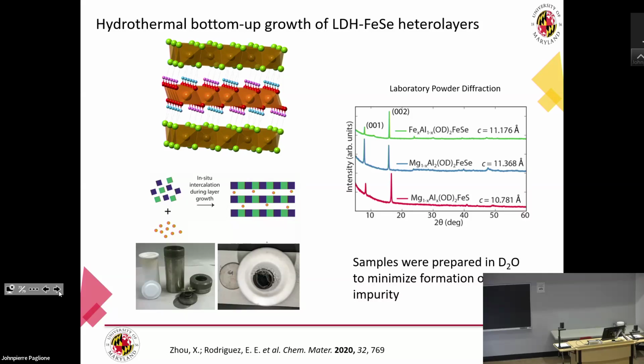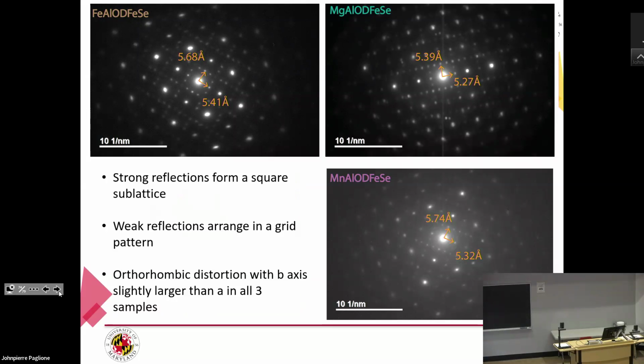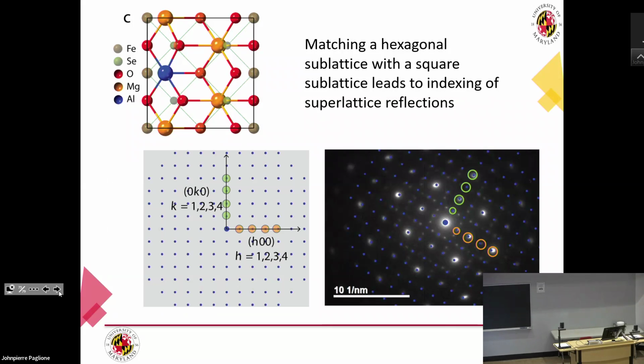and sulfides. And then these are a little bit hard to see, but these are their electron diffraction patterns, and we can generate these compounds and all these superlattice reflections in them that tell us how to solve the structure, at least, and we can index all these superlattice reflections by taking a hexagonally based layer that's able to strain this square lattice layer of the iron selenide. We haven't gotten a superconductor yet, but we've been able to at least learn how to design them chemically and how to solve the crystal structures.